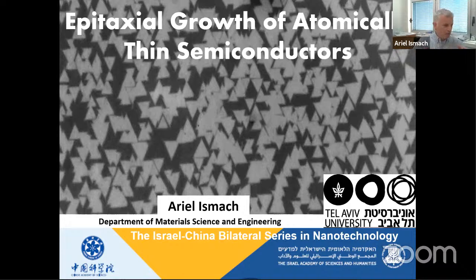So they have covalent bonding or ionic bonding inside the layer, but in between the layers, they have relatively weak van der Waals interaction, and therefore we can basically isolate single or few layers of these materials. And also because of this anisotropy, we can grow them at the single layer level without the need of unique equipment in ultra high vacuum and so on, but by, as I will show you in a minute, very standard and simple equipment. So in this slide, you can see that this family of layered compounds is huge.